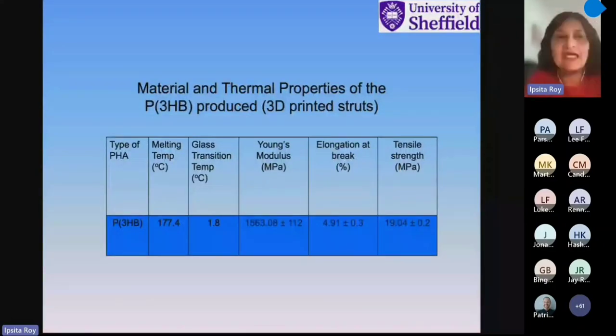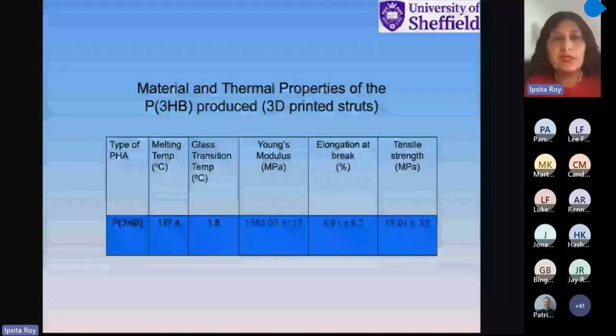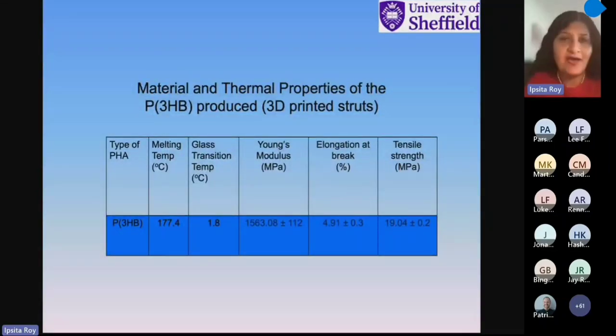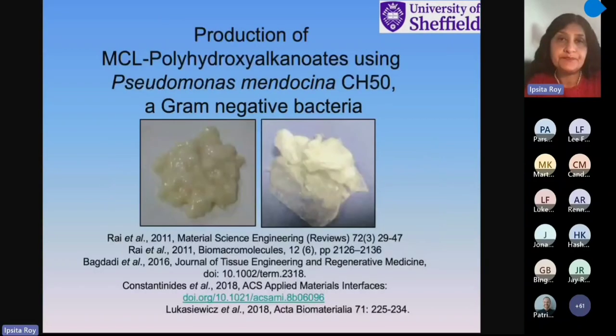And here you can see it's a high melting polymer. This is a 3D printed strut. Glass transition is about 1.8, so quite low. Young's modulus is about 1,563 megapascal. Elongation at break about 4 or 5, not very high, and tensile strength about 19 megapascal. So quite rigid, getting close to a gigapascal in terms of its Young's modulus.